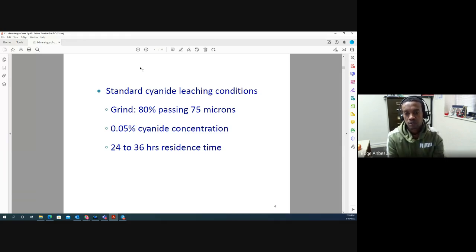You take the residue, separate it out, and you take the filtrate and you analyze for gold. So when you started before leaching, you have a sample with a known amount of gold. After leaching, you have dissolved the gold out. If all the gold was dissolved out from the sample, you have, say, 100% recovery, which doesn't occur in reality. But the idea is, I know what I have started with. I now leached it, dissolved it, and depending on how much gold is left undissolved, we can work out how much has dissolved. So the recovery is based on how much has dissolved.